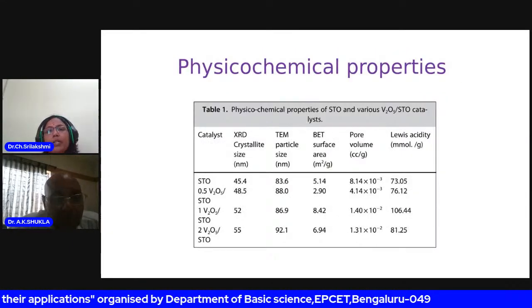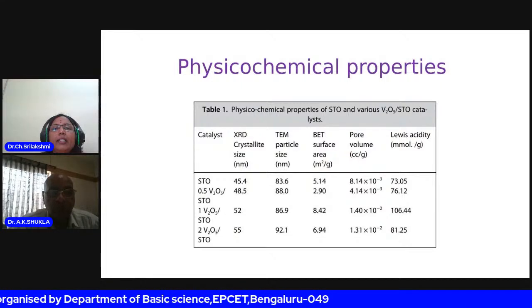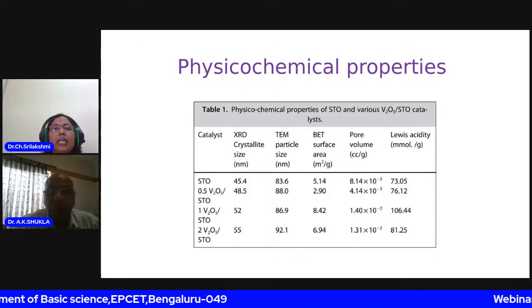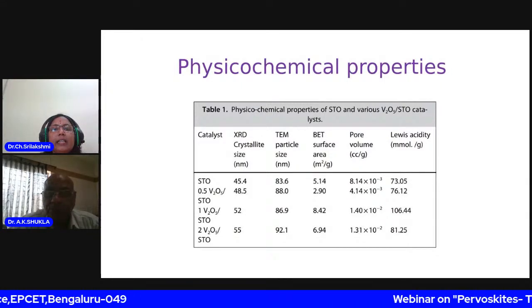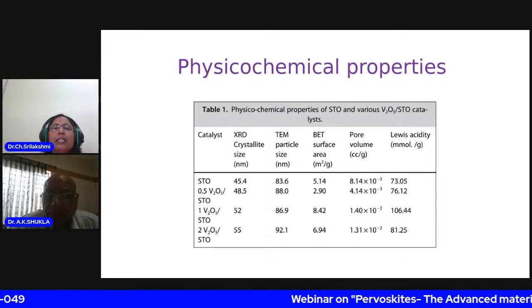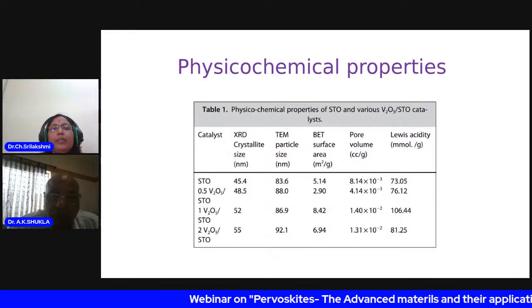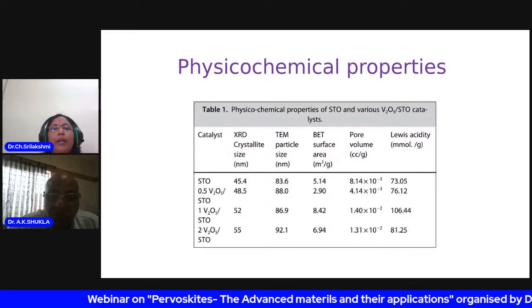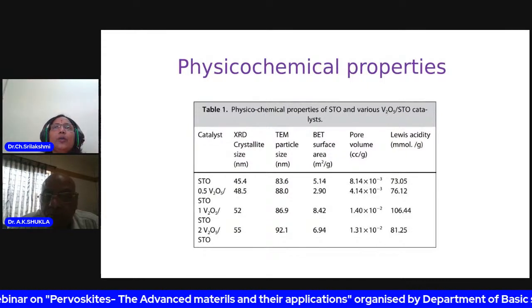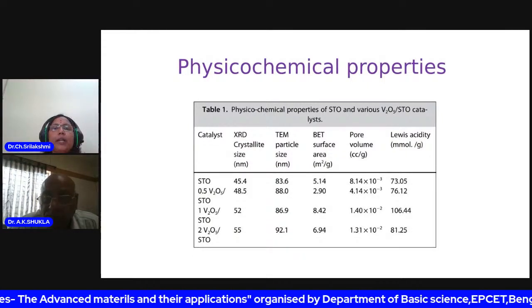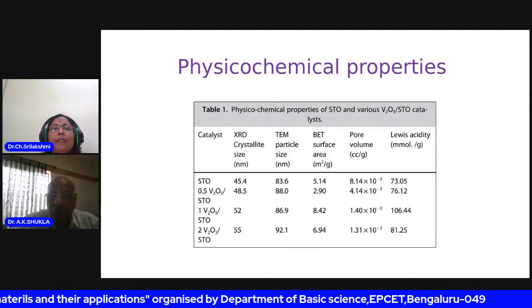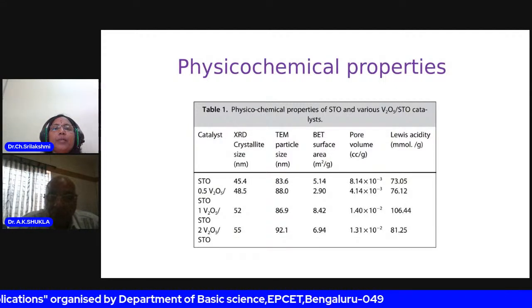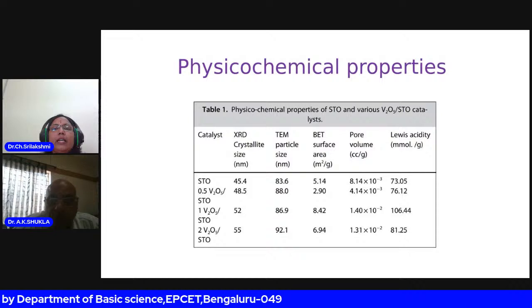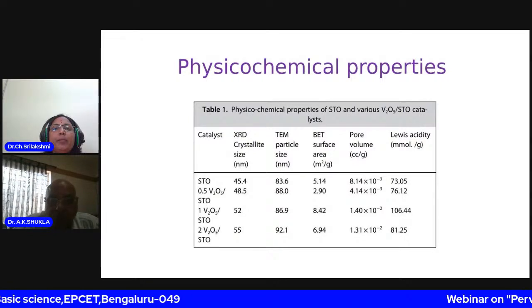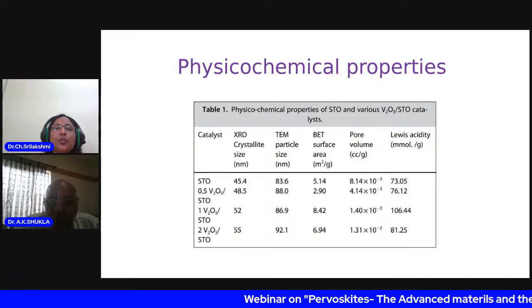So what is this? Whether it has an effect? And again, these are the physicochemical properties you can see. The crystallite size is increasing here, because this increase in crystallite size is in good agreement with the increase in the particle size. Why is this increasing? Because the morphology is changing from spherical to plate-like structures, and the surface area of the pure strontium titanate is 5, and it is a little lower at 0.5. What does it mean? At low concentration the vanadium is nicely sitting in the pores of the strontium titanate.